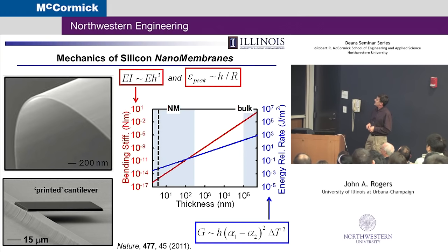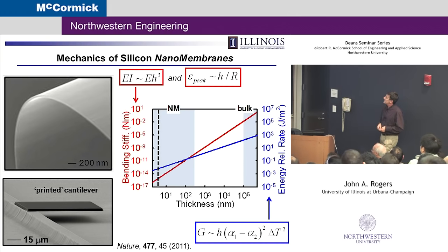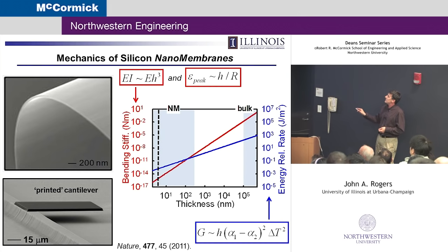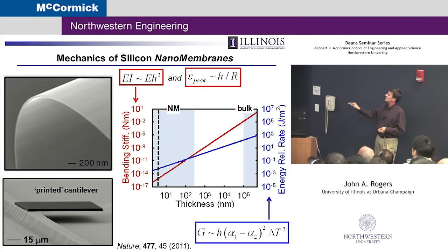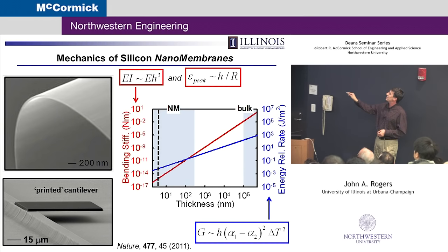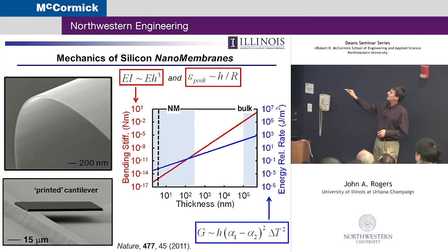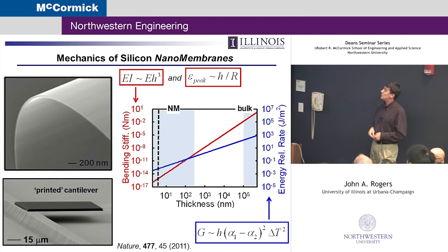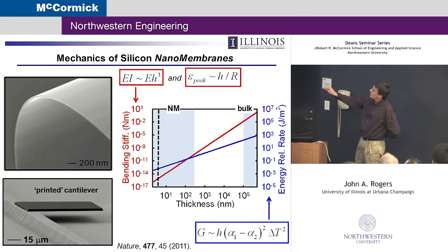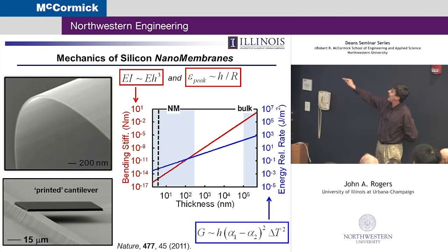That's interesting for a number of reasons that tie back to very elementary considerations in mechanics. So it's really mechanical engineering. The first one of which is that the bending stiffness, the resistance to bending of a sheet of material like that, is proportional to the product of the Young's modulus of the material. We're sort of stuck with that with silicon, 150 gigapascals, but it scales like the cube of the thickness. And so as a result, if you plot bending stiffness as a function of thickness, it's just Newtonian mechanics. It takes you from a bending stiffness at a wafer format of about 10 Newton meters down to about 10 attonewton meters in this nanomembrane form. So that's just classical scaling, pretty elementary aspect in bending mechanics.